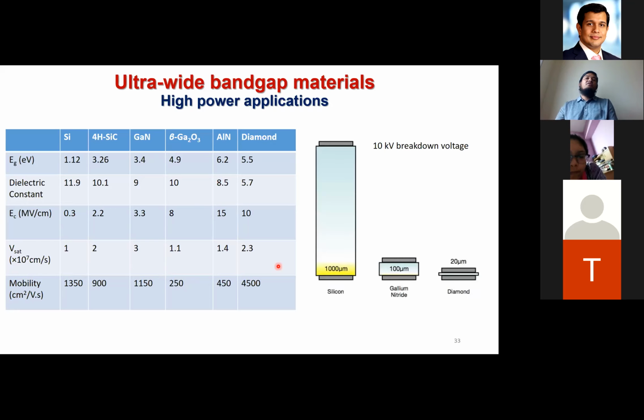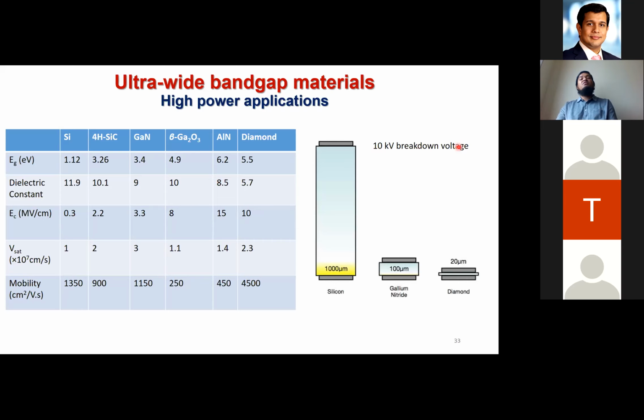For example, if you want a 10 kilovolt breakdown or blocking voltage, silicon, because of its narrower band gap, would require a 1000 micrometer thick drift region. If we move to gallium nitride, because of its wider band gap, to support the same voltage we'll need only a 100 micrometer thick drift region. If we go to diamond and support the same voltage, we will only need a 20 micrometer thick drift region. This sums up why these ultra wide bandgap materials are very promising and why the community is so excited.